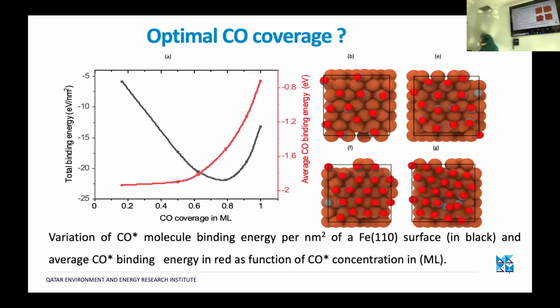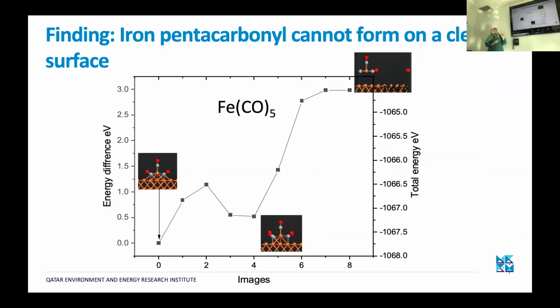The thing is that what we found, despite all attempts, is that the iron pentacarbonyl actually cannot form on a clean surface. Okay, so we did each and everything. And here you have a lot of possibilities and scenarios that you need to consider. And you found that from the energetic point of view, the iron pentacarbonyl cannot form on a clean surface.